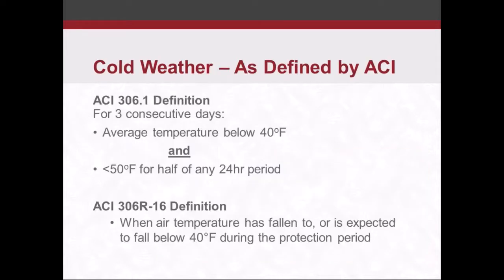So how does ACI define cold weather? They've got a couple of different definitions depending on what document you're looking at. ACI 306.1, which are the ACI specifications for cold weather concreting, defines cold weather as 3 consecutive days of average temperatures below 40 degrees and less than 50 degrees for half of any 24-hour period. So both of those conditions have to be met for it to be considered cold weather by ACI specifications.